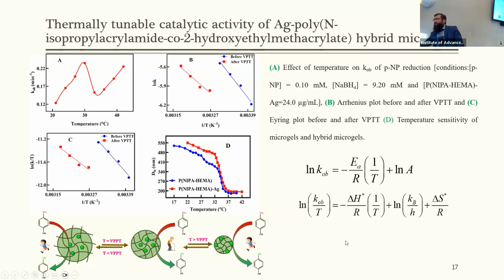We also used the Eyring equation for the determination of activation parameters. For this purpose, the log of k over T was plotted as a function of 1 over T, as shown in this figure, and the enthalpy of activation and entropy of activation were evaluated from the slope and intercept of the Eyring plot before and after the volume phase transition temperature.